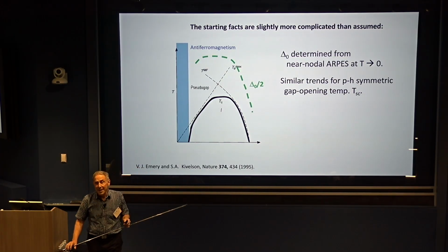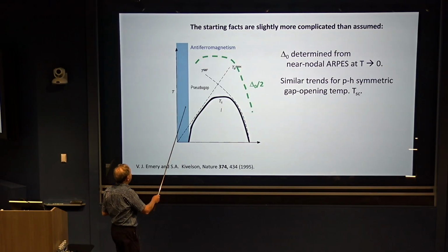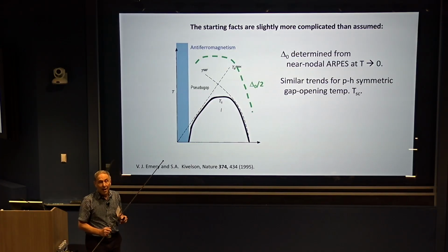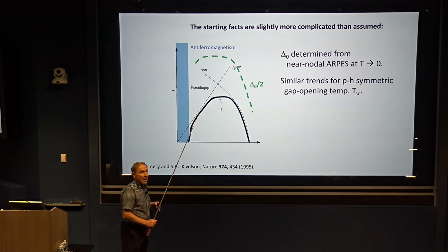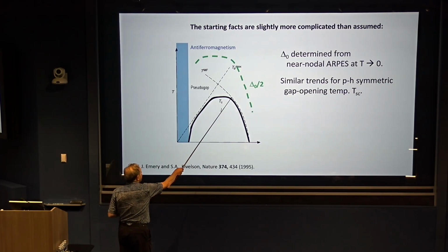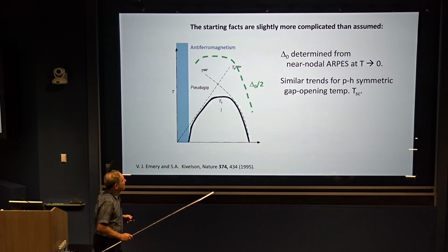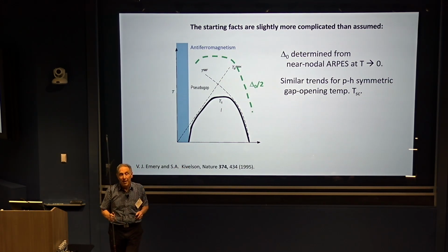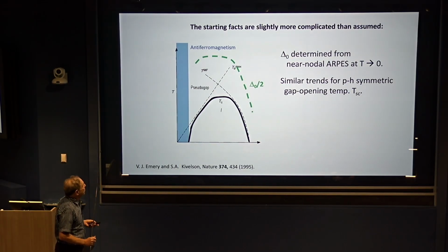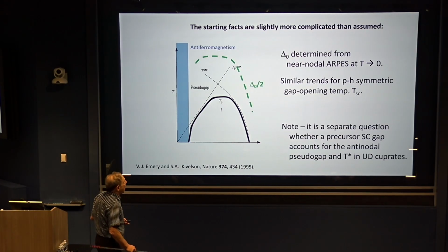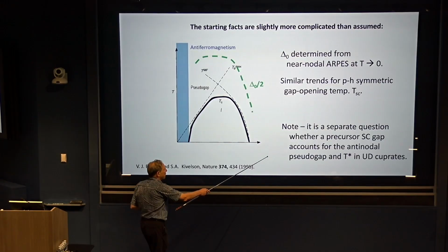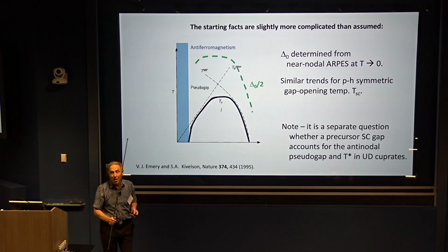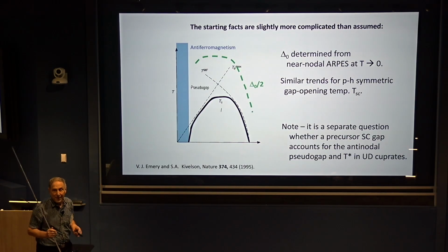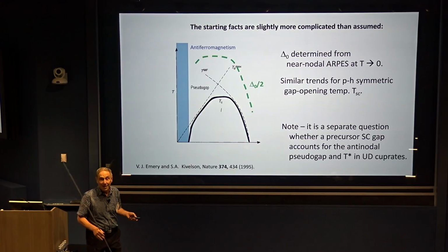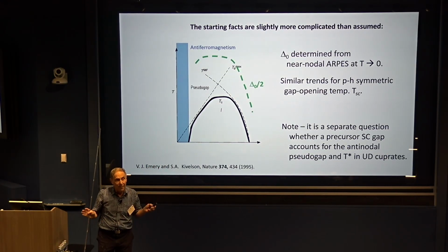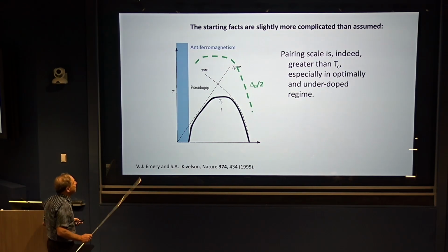You also do see evidence of gaps that open up above TC. That's what pseudogap meant here. It's a little less clear which of these are superconducting gaps, but even over here, for instance, Yuhei has shown data that show a particle-hole symmetric piece of the gap that opens up somewhat above TC. So that part of this picture doesn't look so bad. I should say it's a completely separate question whether T star and all of the pseudogap phenomena seen above TC are related to superconductivity or to other things. This is just talking about the superconducting component of whatever gap we're looking at. Okay, so that's good.